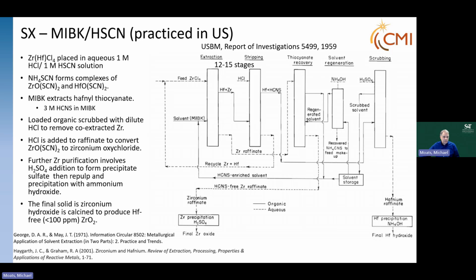So we have a solvent extraction stage where the feed material comes into contact with the organic. We have thiocyanate coming around. The organic loads the hafnium, and gets a little bit of zirconium on there, so it has to be stripped off. We use HCl to strip the zirconium. The strip or scrub comes off and comes back around. The zirconium that doesn't load is the raffinate. We recover the thiocyanate by adding HCl here. So the thiocyanate is regenerated and sent back around.